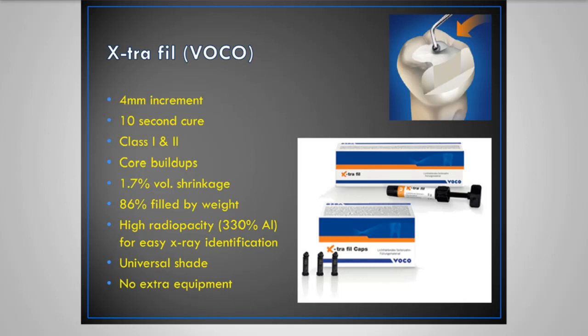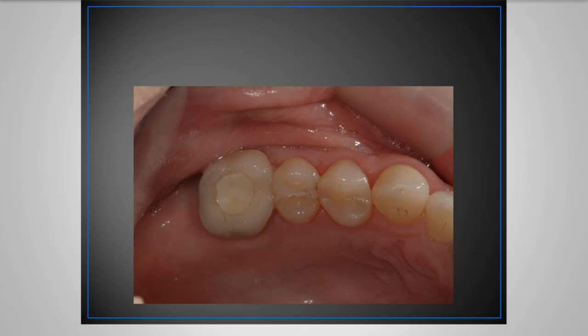So this particular product, again, I would say to use the Compules because you can get compression of the material as you're forcing it into the defect. And at 1.7% volumetric shrinkage, it's very low for the Voco product, but being heavily filled at 86% gives us great wear properties under pressure in the posterior dentition. They have a universal shade, which looks great. It's not transparent and giving a gray appearance. So being that it looks like natural tooth structure makes this very desirable if you're placing a large bulk of material. And you don't require any additional instruments or equipment. You can use it in your traditional composite gun, which makes it easy for adaptation and modification in practice.